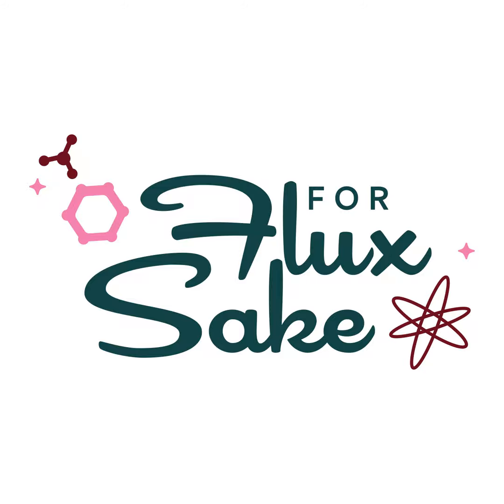But if you don't have boron, because historically people didn't ship materials all over the way, how are you going to get your temperature down and get a stable glaze? Well, historically, people would use lead. That's what lead glazes were, is that lead works at lower temperatures. But the other alternative, a lead-free alternative, was what they call a Bristol glaze. And a Bristol glaze, the origin is controversial. Bristol, England tries to take credit for it. That's where the name Bristol comes from. It was probably actually developed in the US. That's what history points towards the chemistry being from.